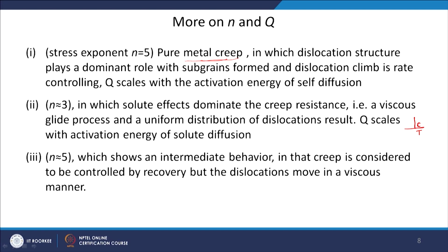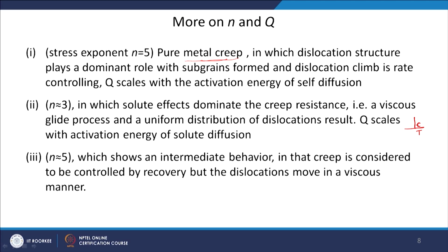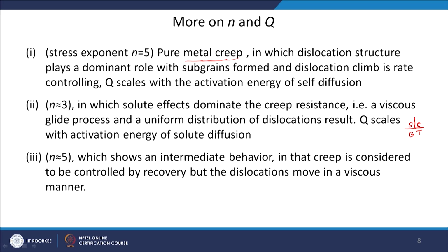So, if you have solute atom in the material, at high temperature solute will also be able to diffuse. If the solute atom is of bigger size than the matrix, then those solute atom will go and sit where the tensile stresses or tensile strain are there, because the bonds are stretched there, a bigger atom can easily sit, and this tensile compressive will balance out. Whereas if the solute atom is of a smaller size, it will like to sit where the compressive stresses are there, because already atoms are compressed, a smaller atom will help them to reduce the strain energy. So, a smaller solute atom will sit in the upper side, a bigger solute atom will sit in the tensile side.